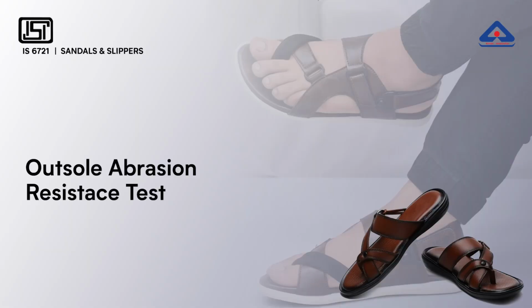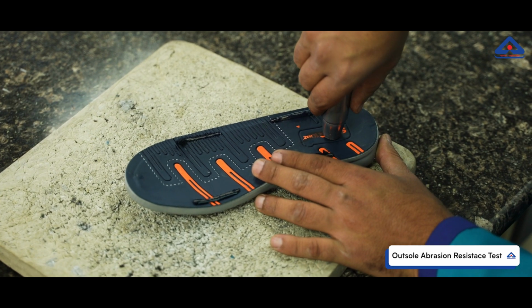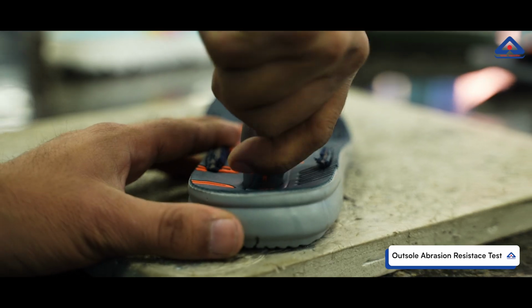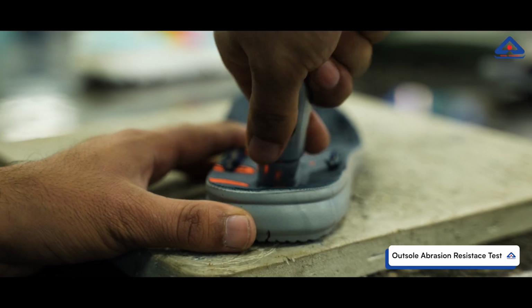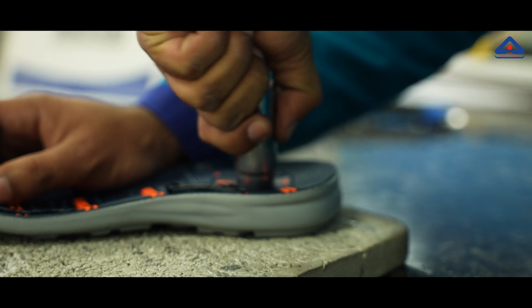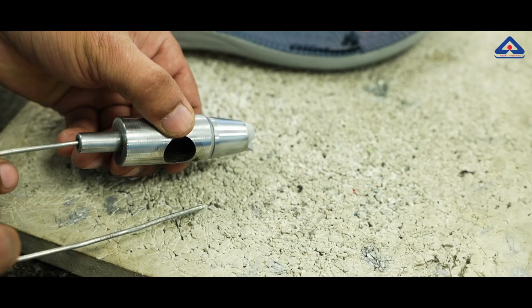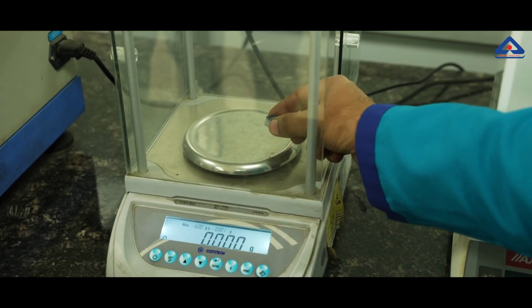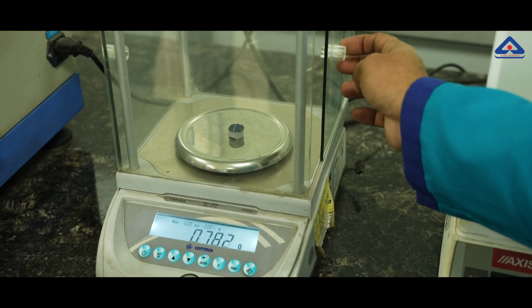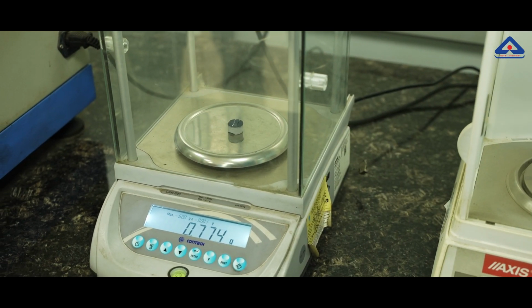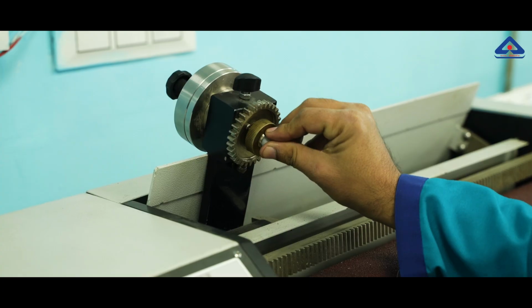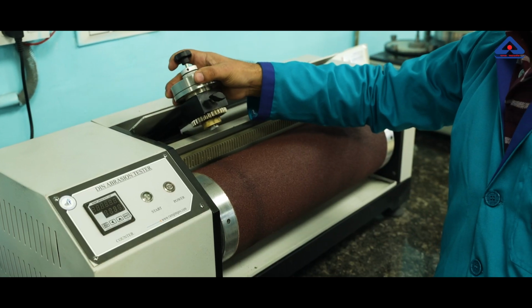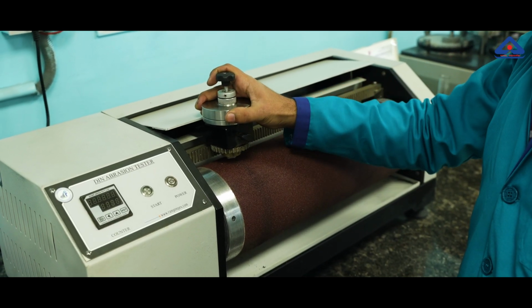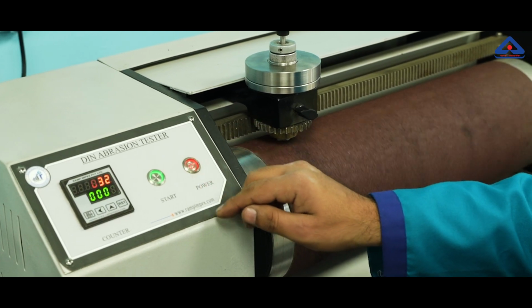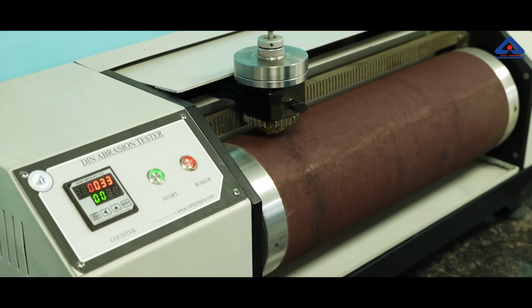Next, we have the abrasion resistance test. Outsole abrasion resistance of non-leather outsoles is tested by applying a vertical requisite force over an abrasion distance of 40 meters. In this test, pieces may be taken from anywhere on the sole. After completion of the test, the wear is checked by comparing the loss of mass of the test specimen and the loss of mass of the standard reference material. This test replicates the effects of rough surfaces on the sole, assessing its durability.